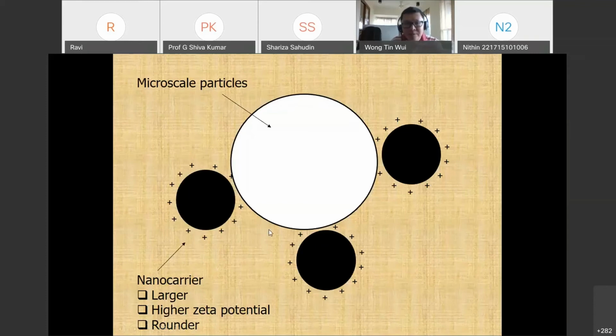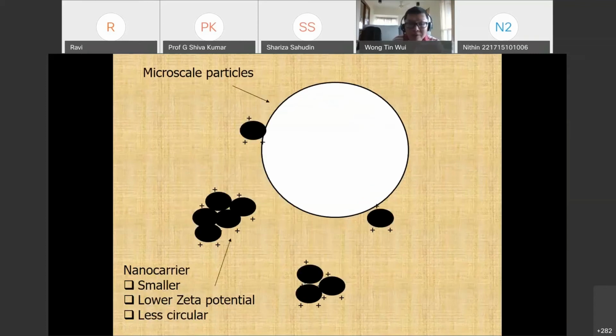Now, on the contrary, if the nanoparticle is very small and not circular in shape, it will exhibit a large specific surface area. Such nanoparticles tend to aggregate between themselves instead of absorbing onto the microscale particles for transportation into the deep and peripheral lung. Likewise, if the nanoparticle has lower surface charge, lower zeta potential, they will aggregate between themselves instead of interacting with the microscale particles for inhalation, right?